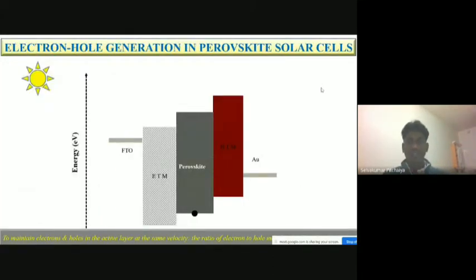This is the mechanism behind the working of the perovskite solar cell. You can see h nu energy hitting the perovskite layer, and there it generates electrons, that is the exciton. It splits the exciton into electron and hole pairs. Further, these generated electrons and holes move towards the respective transporting layers, and further they are expelled out through the conductive electrodes. This is how it produces electricity.